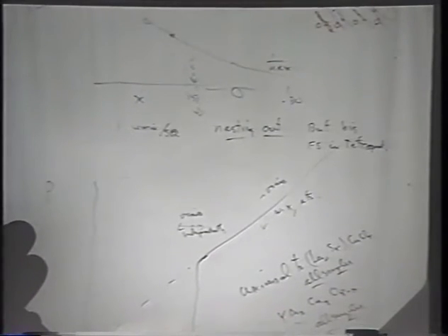The transition does not change any bond distances, and doesn't change seriously any lanthanum-oxygen bond or any copper-oxygen bond angles. All it does is an alternate twist of what we in our theory call the red coppers and the black coppers, the red coppers being turned to the right, say, and the black coppers to the left, as you look along one of the diagonals in the basal plane.